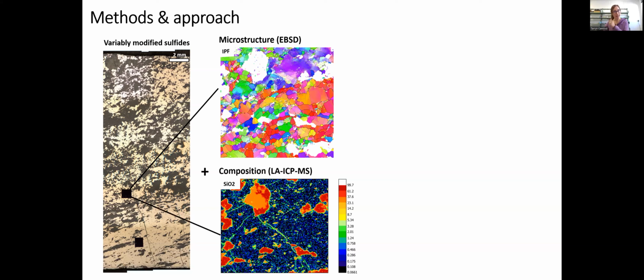Then I'll go and raster the same area with laser ablation ICP-MS, and that is to map out major and trace element composition. So this is just an element map for silica. I'll have different legends on these, but I'll always have warmer colors being higher concentrations, even if the numbers change. And as you'd expect, silica is quite high in the feldspar and chlorite, and really low in the pyrrhotite.